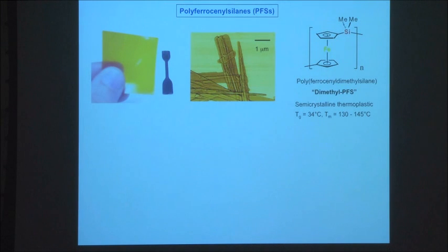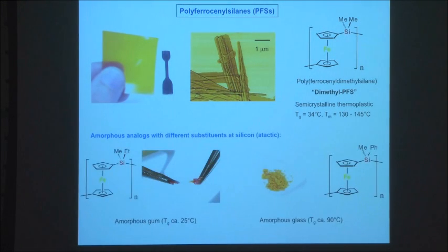If you go from two methyl groups on silicon and just replace one of the methyls by another group, such as ethyl or phenyl, these structures now are not symmetric, and these can no longer pack into a crystalline lattice. And so these materials are completely amorphous. And you see this just going from the dimethyl material to the methyl ethyl. You go from a film-forming thermoplastic material into this amorphous gummy material here. With phenyl here, it's also amorphous. It's a glassy polymer, but there's no crystalline order here. So if you look by X-ray diffraction, you see no order for these materials, whereas this shows sharp peaks due to the scattering by the crystallites.